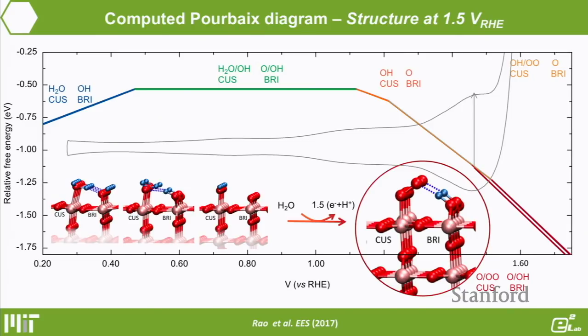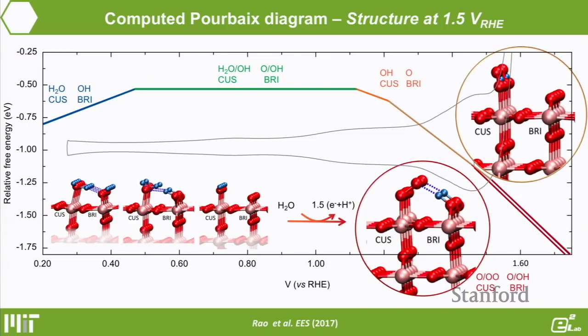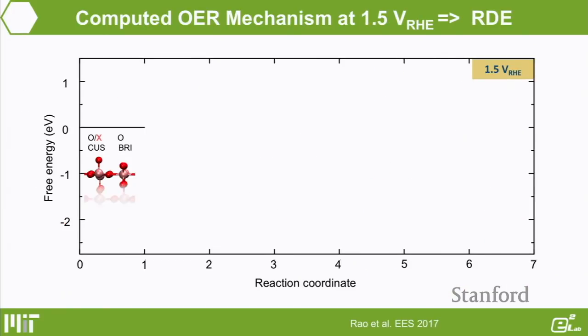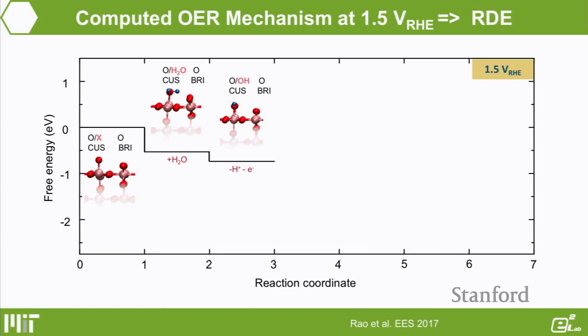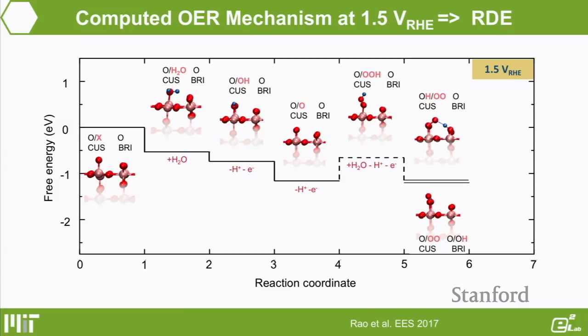And this is, to our knowledge, one of the first pieces of evidence supporting that: this O2, more like a superoxide-like species, can be limiting on the ruthenium-110 surface. And there's another configuration, where this O2 can be stabilized by neighboring protons at the Cus site. So you can perform this type of energetics landscape for oxygen evolution, and you'll find essentially that removing this O2 is really limiting, is energetically uphill.